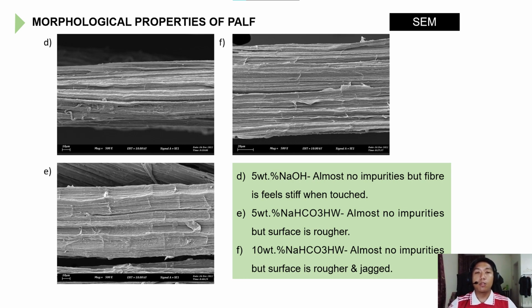Next, we have the 5% NaOH and 5% and 10% of sodium bicarbonate with hot water. From these pictures we can see that the fiber surface is much cleaner compared to the untreated fibers from before, and also they have a much rougher and jagged surface compared to the untreated fiber. However, when I am handling them, I could feel that they feel a bit stiff and a lot rougher to the touch compared to the fibers before.